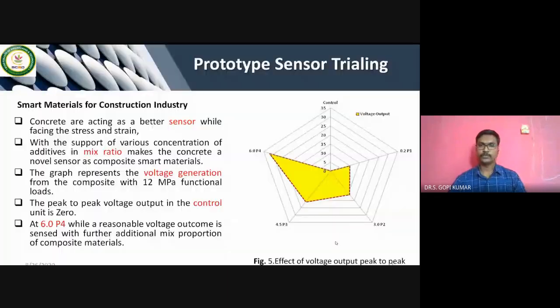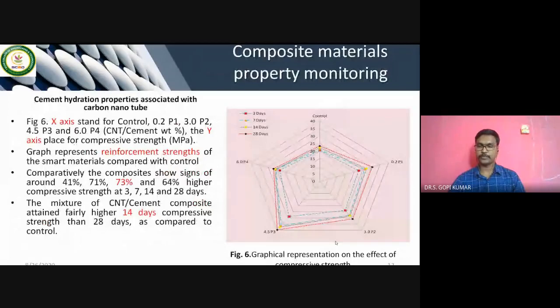Now, the next one, compressive strength. The graphical representation on effect of compressive strength, where in this image, for control, 0.2, 3.0, 4.5, 6, the compressive strength is evaluated for 3 days, 7 days, 14 days, and 28 days, where the higher compressive strength is observed in 14 days, where it is graphically highlighted.